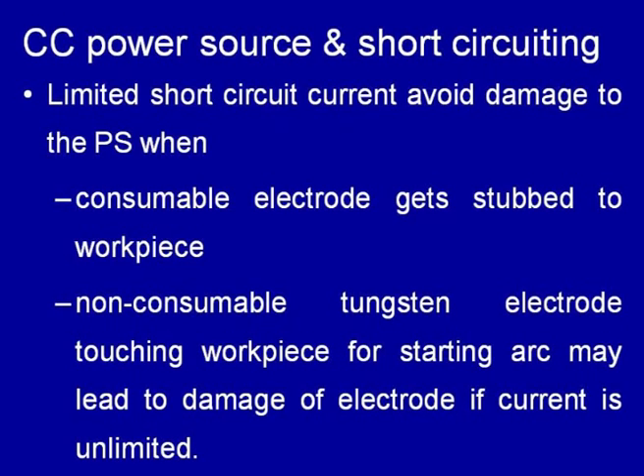Further, another important point related to the constant current type of power source is the short circuiting. We know that short circuiting can take place during welding due to carelessness, or short circuiting is done intentionally while initiating the welding arc. The electrode is touched with the base metal and then taken away, so that the arc is ignited by the touch start method. In the touch start method, the electrode is intentionally brought in contact with the workpiece, while short circuiting can also happen due to carelessness while welding.